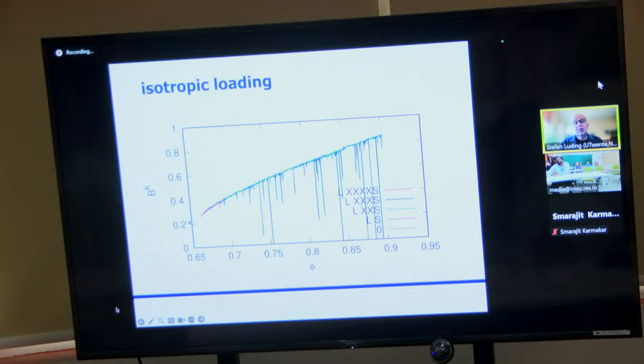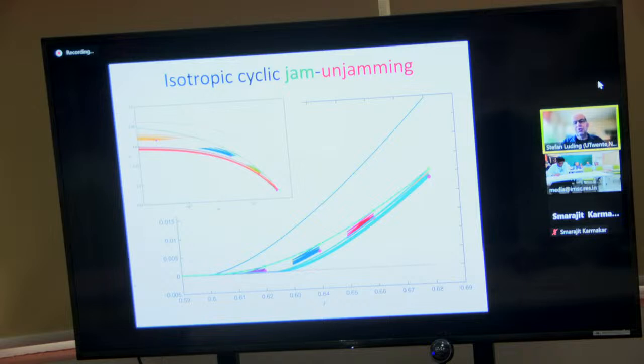For different rates, we do observe the same bulk modulus, and we get different information during the plastic events, where the bulk modulus is not defined, because a plastic event is not elastic. Good. So then you can play the game with the theory and with the simulations.